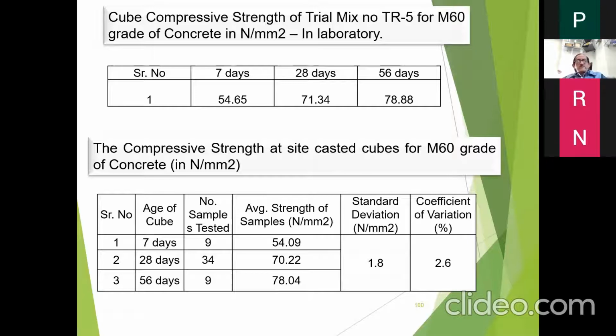28 days and 56 days also, just to see how the strength is increasing with time, because we have used a lot of secondary cementitious material, that is fly ash, and we are required to use it. That's why we assess how much the strength is at 28 days and 56 days. The number of samples tested at 7 days were 9, at 28 days 34, and at 56 days 9.